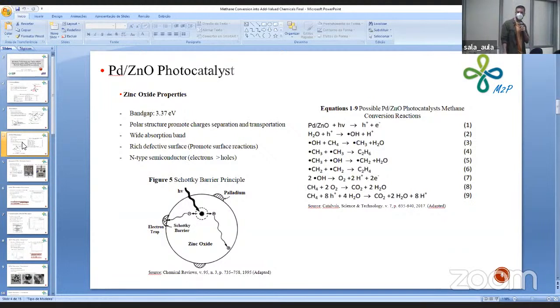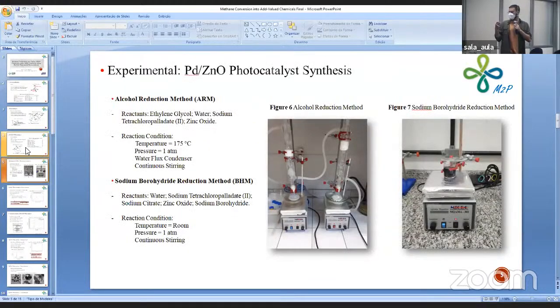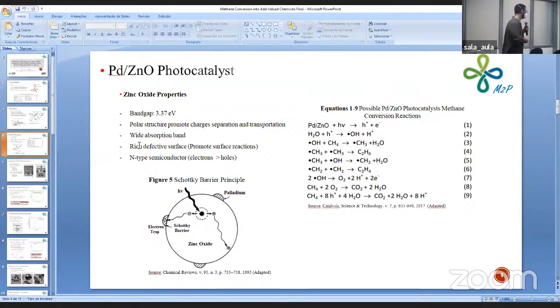In figure 5, we have the palladium nanoparticles deposited on the surface of zinc oxide. And a Schottky barrier at the interface between metal and semiconductor can trap electrons in the nanoparticles and prevent their recombination, the photogenerated charges recombination. In equations 1 to 9, we have some possible reactions that we expect in the system, like the semiconductor activation at line 1, the water splitting, the methane activation itself, and some coupling reactions. Besides that, we have some other reactions that might happen.